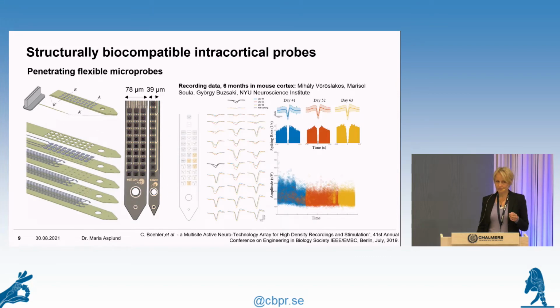We have tested these devices for recordings first of all, so placed them in the cortex of mice and recorded neural signals. So for this group in New York, what they wanted was a probe where they can follow signals from single neurons over time. So they want to see the same signature of the neuron, and that shouldn't change a lot over several weeks, so that they can do studies on learning and memory, and that they can really study the neural circuit in detail. So what we see here is the same neuron that is recorded at each of these electrode sites. And it's also over a period from, I think it's day 41 to day 63, so we can see that the signal is also fairly stable. So we have up to 6 months of recordings with these devices.